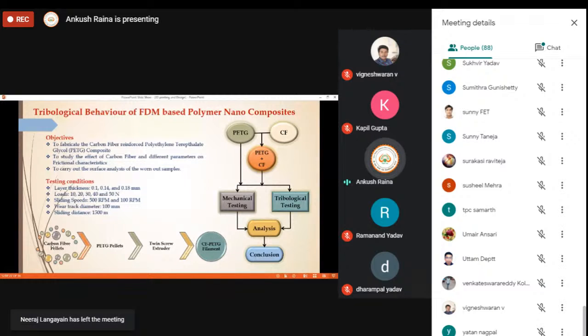Basically, how has this carbon reinforced PETG been obtained? We have the carbon fiber pellets and then PETG pellets. A twin screw extruder has been used to produce this CF PETG. So what were the objectives? To fabricate the carbon fiber reinforced PETG, to study the effect of carbon fiber and different parameters on the frictional characteristics, and then to carry out the surface analysis of the worn out samples. Testing conditions: we use different layer thicknesses, different loads, then sliding speeds, then the wear track diameter, and the sliding distance was kept as 1500 meters.